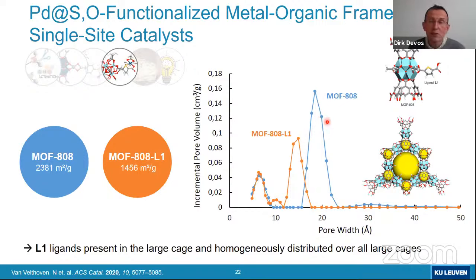And actually MOF-808 has very large pores, and for researchers in heterogeneous catalysis interested in porous materials, you would measure that always with nitrogen physisorption. And actually the MOF-808 as such has very large pores, with a pore width typically, if you measure it with nitrogen physisorption, of 2 nanometer diameter. Now, if you dock the ligand L1, this thioether carboxylic acid molecule, to MOF-808, then you see that you really have a decrease of the average pore size, which is a good proof that this ligand is spread all over the MOF in a rather homogeneous way.